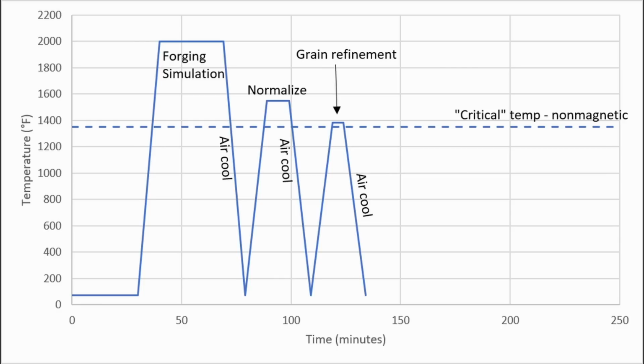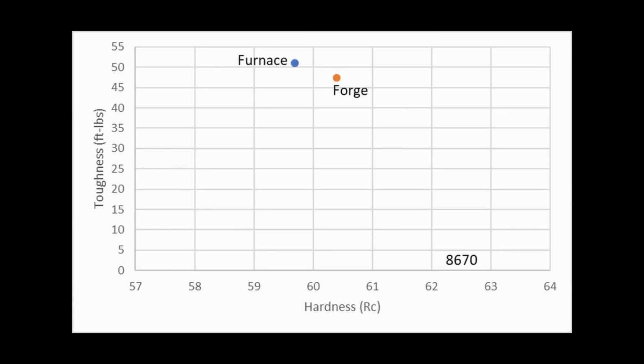The main mistake people make is overheating. You can do all the thermal cycling in the world and have that grain super, super fine, but if you overheat it before quenching, it's going to have a coarse grain and have bad properties. So you heat to non-magnetic, you quench it in oil, and then you temper and it's ready to go. 8670 is one of the steels that I tested with this method, and the properties turned out very similar to what we had gotten with furnace heat treating.